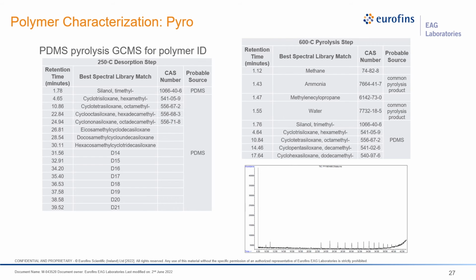The final technique we'll take a look at is pyrolysis GCMS. This involves heating the sample as well, but in two different steps. And instead of observing the mass loss as a function of temperature, we'll actually be identifying the volatile components and gases that come off the sample as it's exposed to these elevated temperatures. The first experiment is a desorption experiment. This heats the sample to 250 degrees C. This will volatilize small organic compounds as well as any additives that may be in the polymer, and we're able to detect them in their original form because most organic species can survive at this temperature.